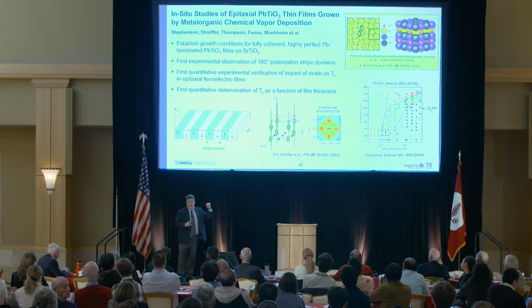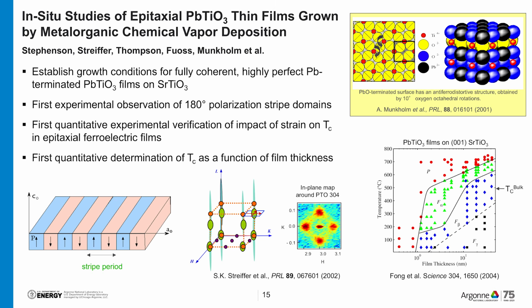Just to hit a few highlights of this, it really was a fun time. We had a lot of work that we were doing on essentially establishing clean surfaces, using that as a baseline by which we could then produce films that were reproducible and whose conditions were known, and then looking at phase transitions in these films in a way which is actually quite astounding. The fact that we were able to measure TCs as high as a couple hundred degrees C above the bulk temperature because of the strain states of these films was really remarkable at this time. And it really set the stage for the fact that this particular type of collective phenomena persisted down to length scales that at that point in time people thought were impossible.